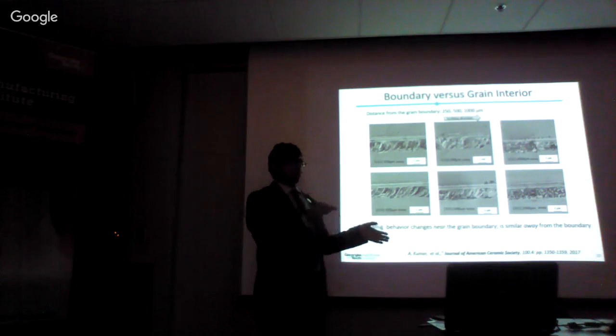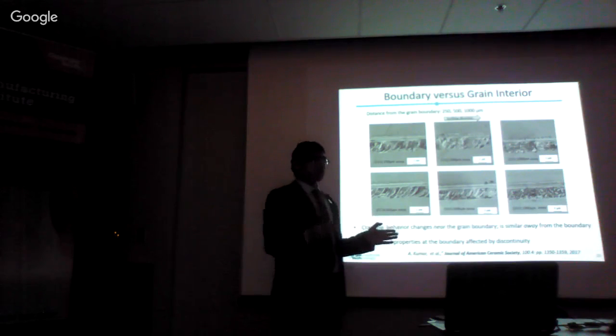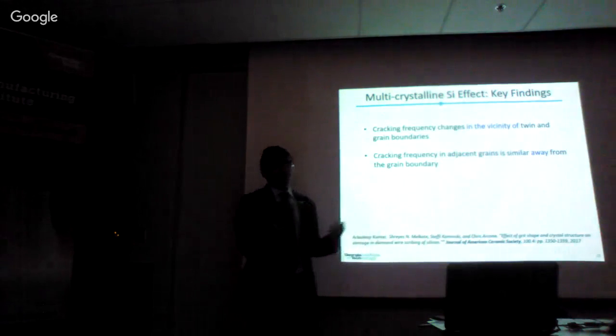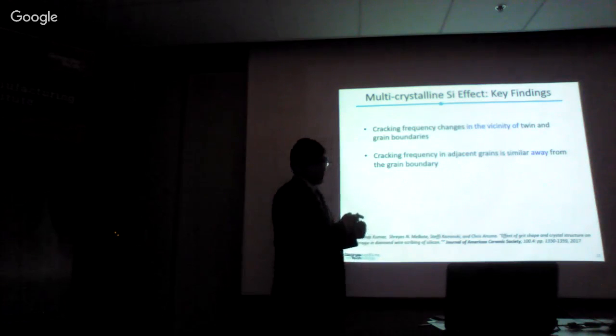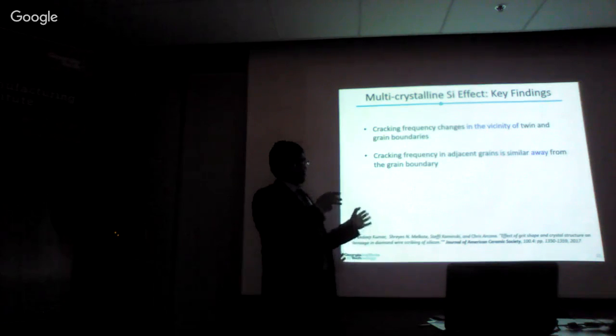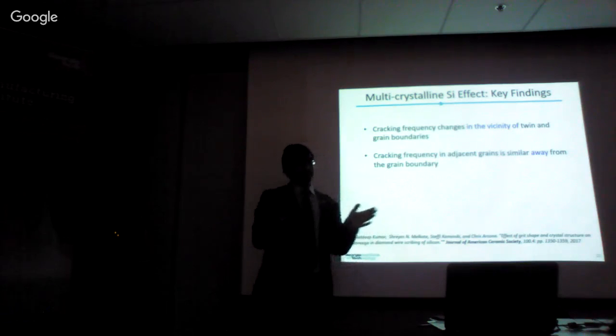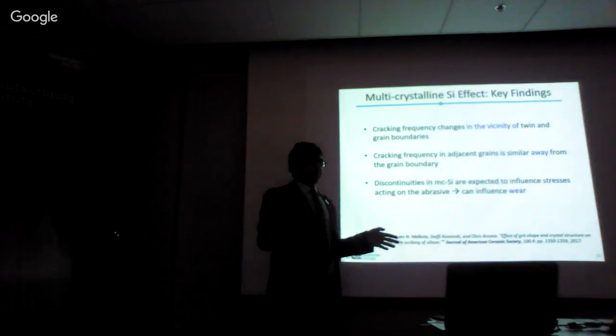So with these results and other results we found, these are representative, we found that the cracking behavior changed near the grain boundary, as we saw in the previous slide, but they become similar away from the boundary. And we hypothesized that the reasons for this are the mechanical properties being different at the discontinuity like grains and twin boundaries, which is creating the differences in the surface morphology or cracking frequency across the boundary. So the key findings or takeaways from this task was the cracking frequency is changing at the vicinity of the boundary, but the frequency in adjacent grains away from the boundary was similar.